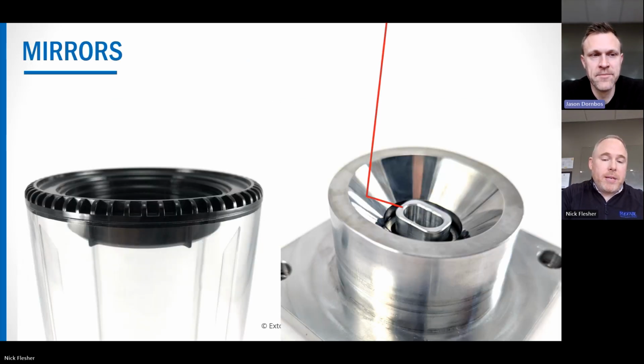There's this quirky thing in laser plastic welding with mirrors. Not all mirrors are created equal. Essentially, we have a fixed scanner or fixed optics and scanner package where we're bending the laser around the profile that you want to weld. When you have undercuts, think fittings with 90s on them, or you want to radially weld an odd shape, like this one to the right, we optically engineer those mirrors to bend the light around that path. You can move the laser beam at up to 3,000 millimeters per second, and therefore get a really uniform heat.